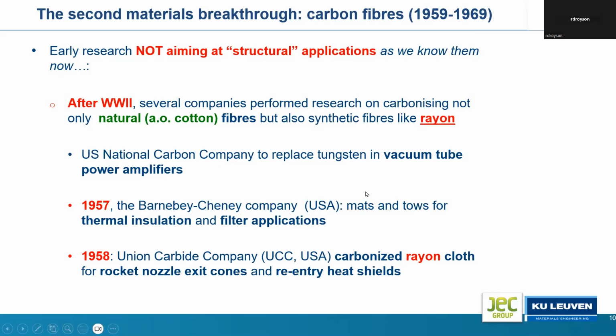1957, there was a development by Barnaby and Cheney for carbonizing natural fiber or rayon fiber mats and tows for thermal insulation and filter applications. And in Union Carbide, and you will see again later on, Union Carbide has been playing a quite important role. They carbonized rayon cloth, rayon textiles for rocket nozzle exit cones and re-entry shields. So all these things were not really aiming at mechanical or structural applications, except maybe the last one, but that was again mainly for thermal reasons that these carbonous materials were used.